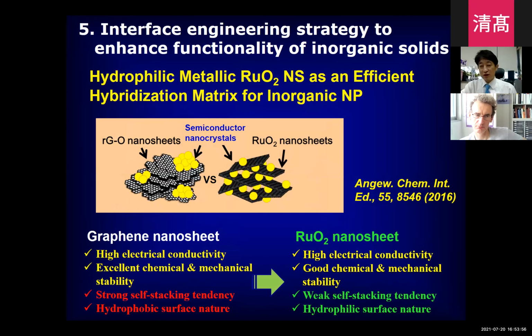Okay. So also we try to tune the interface structure of the nanosheet and hybrid materials. Like many others, we synthesized many graphene-based hybrid materials, but even though graphene is a wonderful hybridization matrix, it suffers from several crucial demerits. One is its strong self-stacking tendency, which is definitely detrimental to the intimate electronic coupling with the hybridized species.